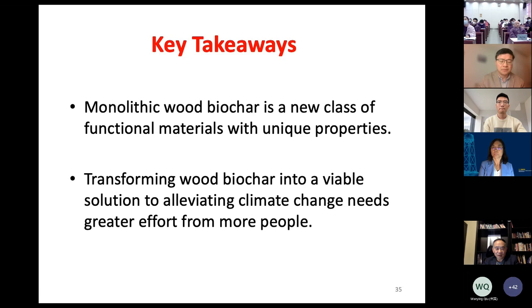Okay, and the major challenge here is the stability of those materials. Those functional groups tend not to be very stable. For example, oxygen-containing groups may disappear after a few hundred cycles. And you were asking a second question about precursors. We are looking at the precursors in terms of porous structures, meaning that we want to have higher porosity and specific surface area. We also want accessibility of those internal structures, so there has to be a good combination of those properties.